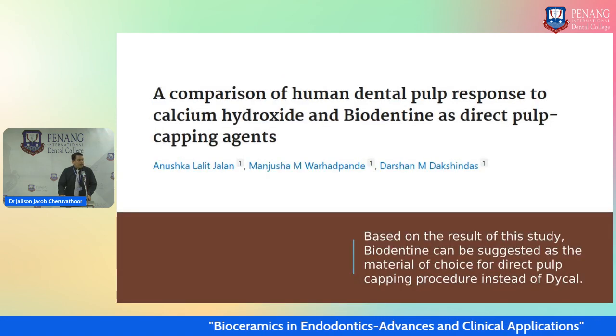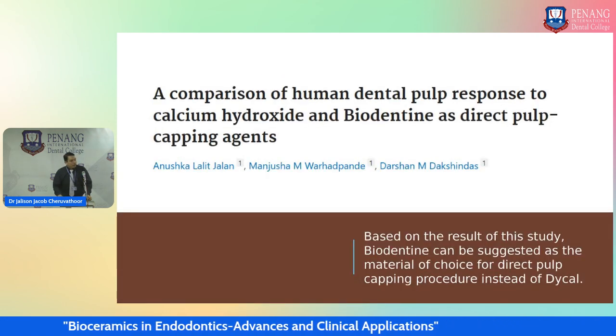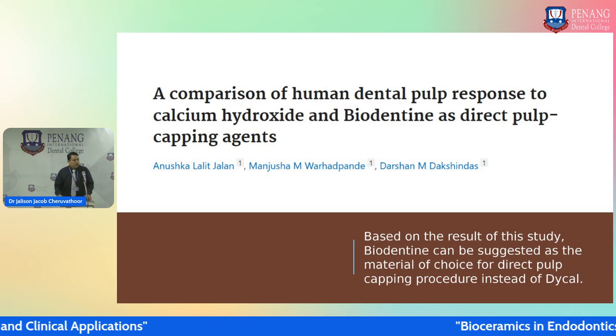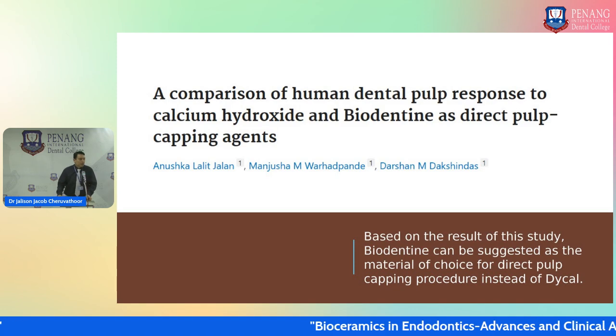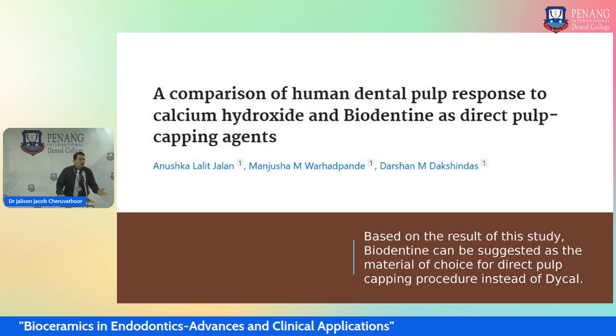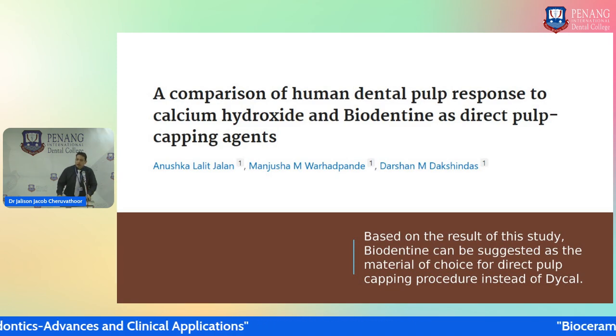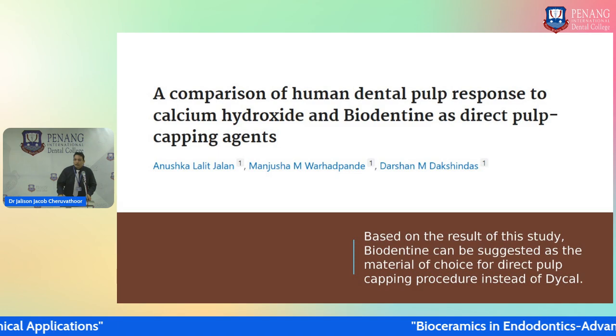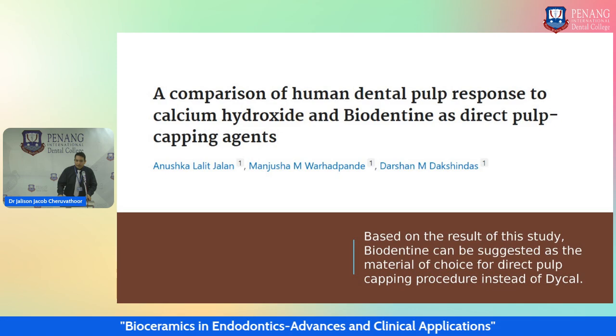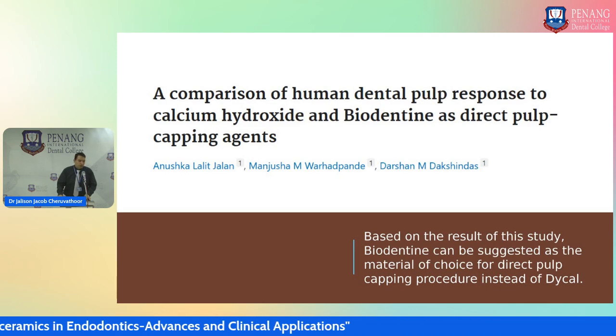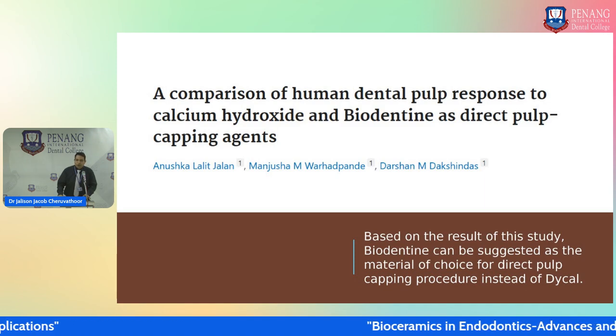Another comparison of human dental pulp response to calcium hydroxide and Biodentine in direct pulp capping. Based on the study, Biodentine can be suggested as the material of choice for the direct pulp capping procedure instead of Dycal, that is the traditional cement. So most of the time when you look at pulp capping cases, we have to have a good seal, and one more thing is that we have to preserve the vitality of the tooth. So a biocompatible material should be placed there to preserve the vitality. Bioceramics are good candidates for that, and the evidence suggests bioceramics such as MTA and Biodentine are good materials to have a successful outcome.